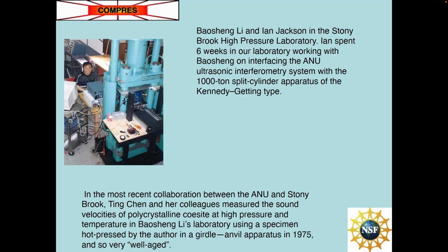And this is Baosheng having learned how to measure the sound velocities using the Jackson interferometry techniques in some of his specimens. In fact, in the most recent collaboration between us and Stony Brook, one of Baosheng's other students, Ting Chen, measured the sound velocities of polycrystalline coesite at high pressure and temperature using a specimen that I had hot pressed in a girdle anvil apparatus in 1975, and for whatever reasons, I still had it. So the people in the laboratory like to say this was a well-aged polycrystalline specimen. Her measurements were done in the last 10 years. Next slide, please.